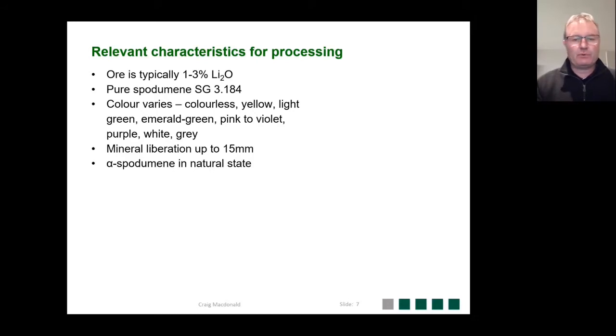Liberation is an important feature, certainly an important factor when looking at a new resource and designing a plant. What we find is the liberation typically occurs somewhere around 3 to 6 millimeters, but in some operations we've seen mineral liberation up to 15 millimeters.